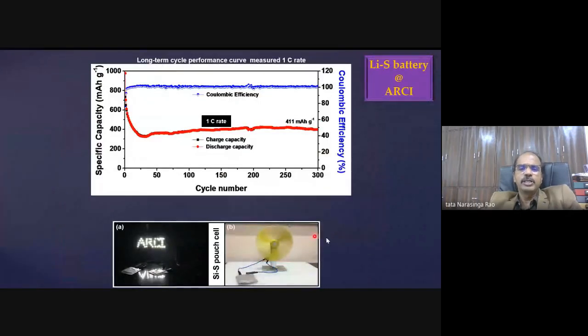Recently we also showed up to 300 cycles at high C rates, meaning higher charge discharge capacity. That means it is a real demonstration for a practical application in electric cars, because when you drive very fast, it is around 1 C rate, and I get 400, which is double that of a conventional lithium battery. That means instead of 200, I can travel 400 kilometers, which is a very big driving range.